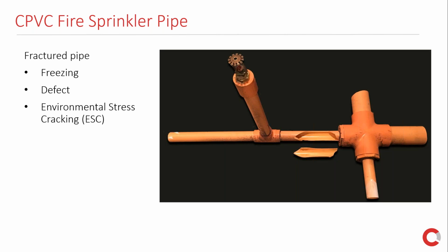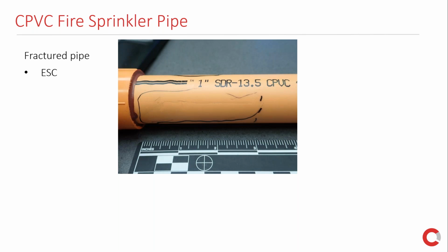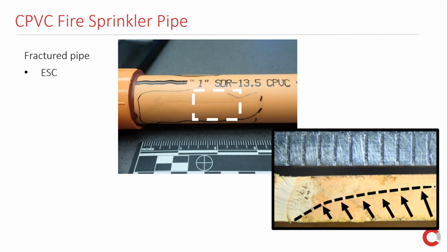So a fracture on a CPVC pipe can have a very similar look, even if it results from a failure mechanism such as freezing, manufacturing defect, or environmental stress cracking, ESC. Careful analysis and evidence identification is required to determine the correct cause of that failure. The failed pipe in this particular case suffered from environmental stress cracking. So when looking at the fracture surface, it was clear that the crack had progressed from the inside towards the outside of the pipe. This was a clear sign that the contaminants were inside the pipe, and it allowed me to focus my attention on what was inside the pipe rather than taking the time to investigate what was outside.